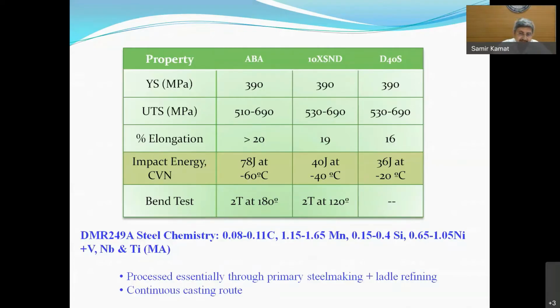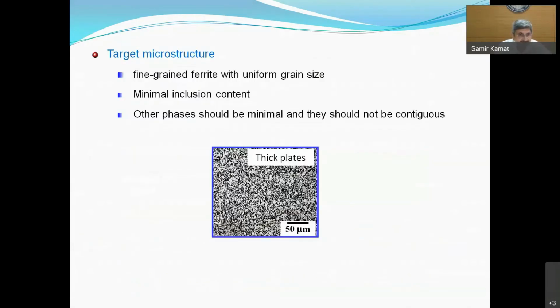Luckily, the Indian steel making industry is fairly mature, and we could find a very good partner in SAIL. And we could, using primary steel making plus ladle refining, and eventually settling on a continuous casting route, though we initially started with the ingot route, we could make this steel with a targeted microstructure which you could get from literature, that is a fine grain ferrite with uniform grain size, minimal inclusion content, and very little pearlite which is not contiguous. So using the processing available at Rourkela, we could achieve such a microstructure.